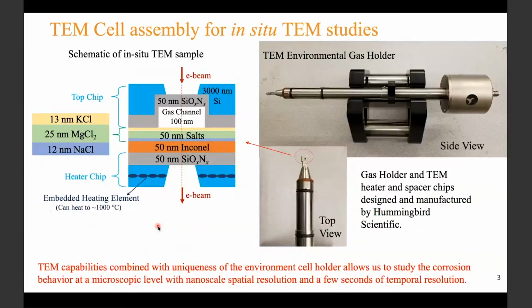But before the actual corrosion experiment inside the high resolution microscope, I had to overcome the most challenging part of my corrosion research: the fabrication of a miniature version of the CSP alloy and molten salt system, and to confine that to a 2-micron area at the tip of the microscope holder that you see in this picture. I spent more than a year of my PhD to build this cubic millimeter, where I deposited thin films of the container alloy, which is Inconel, and thin films of salt layers on a heater chip, which can be heated to around 1000 degrees centigrade inside the high resolution microscope